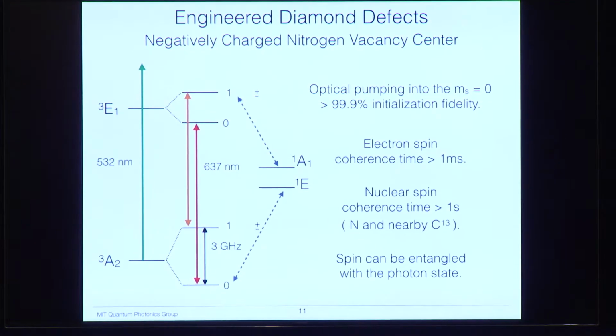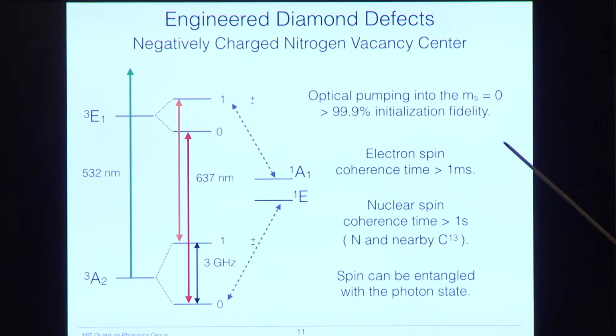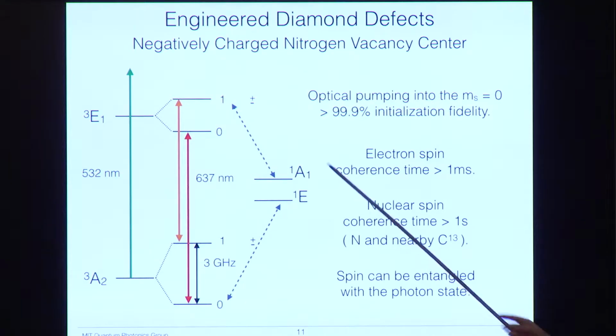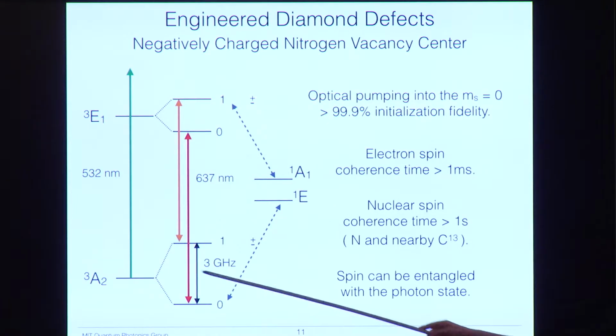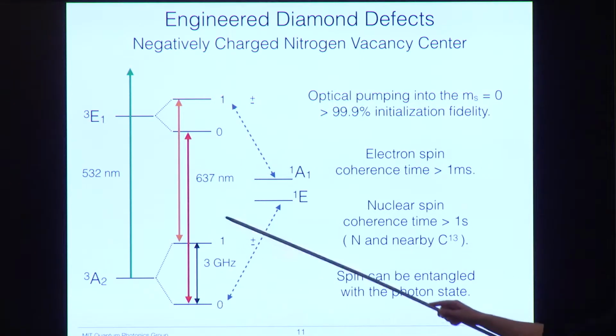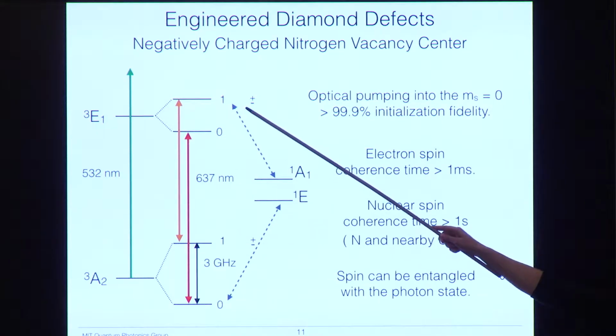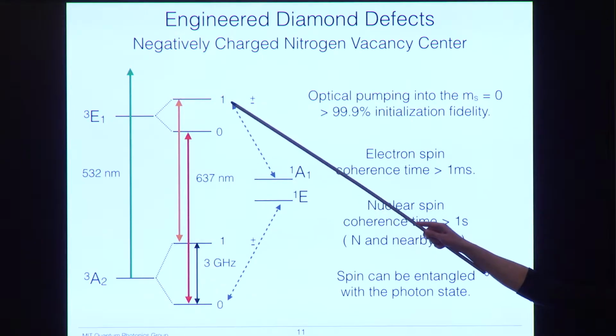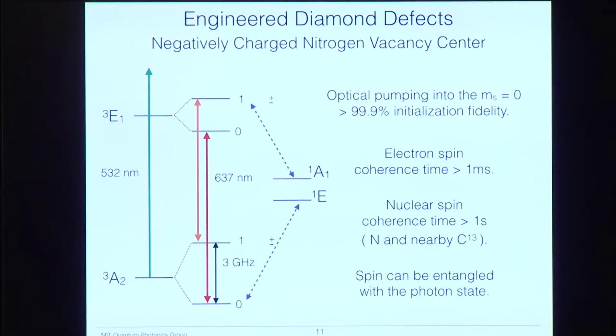There are a few things that make the NV Center so good for quantum information processing. The first is that we can initialize the qubit with very high fidelity. If you notice, there's a state over here. The ms equals 0 spin state is more or less cycling. So if we excite it to the 0 state, it'll fall back down into the 0 state. Whereas the ms equals plus minus 1 states are coupled to this long-lived singlet state, which then decays into the ms equals 0 state. So if we just pump with green enough, we'll pump all of the population, all 0 and 1, into the excited state, and then the 0 will fall back to the 0, and some of the 1 will fall back into the 0 as well, and so if we wait long enough, we can get perfect pumping into the initialization into the ms equals 0 state.